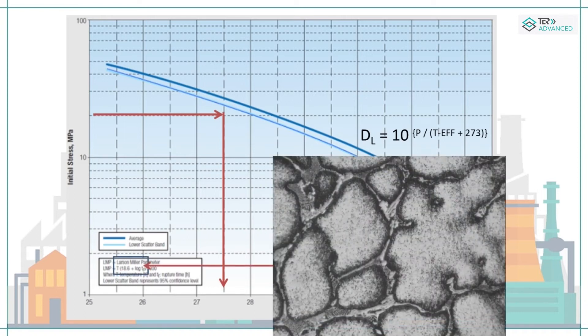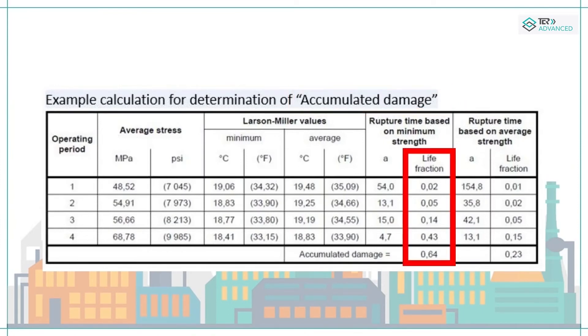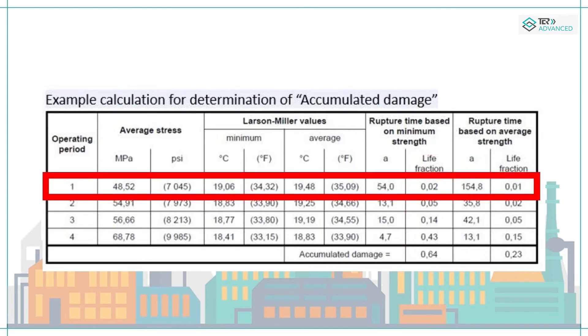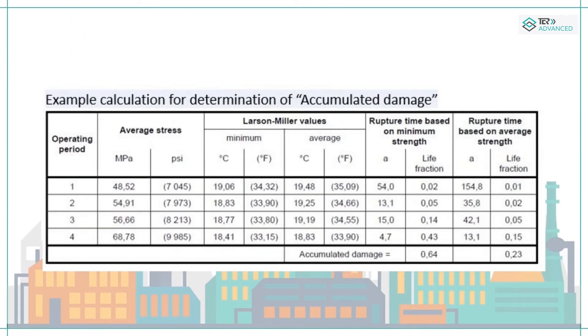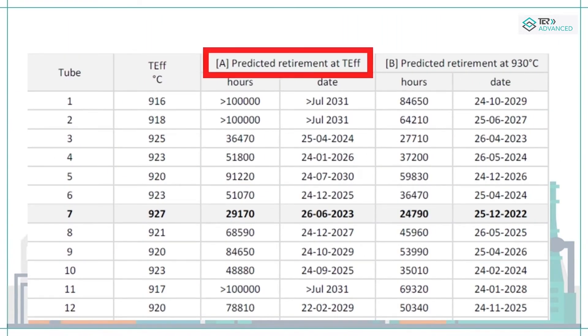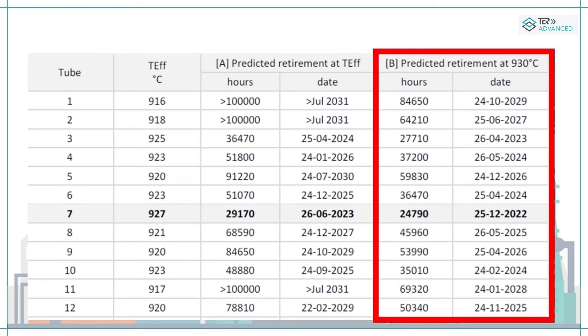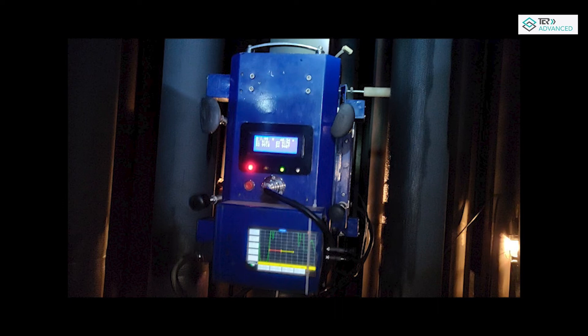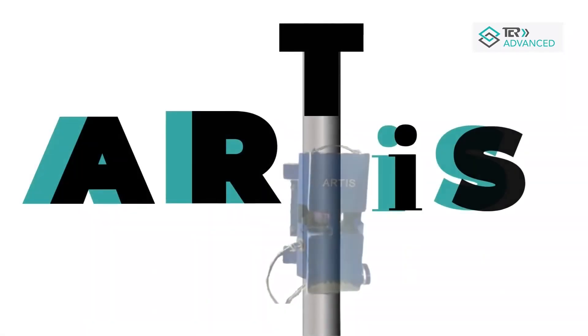The stress versus LMP curve provides instantaneous life at the pre-calculated T-effective for the current microstructural condition. This value becomes the seed for accumulated creep damage calculation. Accumulated creep damage is obtained for different time intervals, calculating the fraction of life expended to instantaneous life for each interval as per guidelines in API 579 / ASME FFS-1 Part 10 and API 530. The remaining life for each tube can be predicted, and a sensitivity analysis obtained for different future operating conditions to optimize tube life. This RLA approach by RTS has been established since 2012.